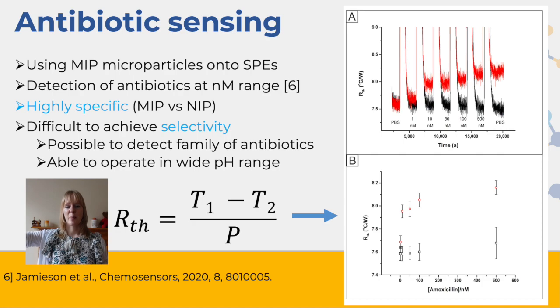And we see there's a gradual step for your molecularly imprinted polymer when you start to increase the concentration. And a spike means that every time we did a new addition, as soon as you introduce some liquid to the system, you will see a temporary drop in the temperature due to the addition of a cold liquid. But then, as soon as it stabilizes again, for the NIP you almost see a spike, and then it's back to the baseline. But if there's binding to your polymer material, your baseline will end up higher. And that's because binding increases the thermal resistance at the solid-liquid interface. And you can use that to convert it into what we call a dose response curve, where you look at your response, in this case the thermal resistance, and we look at a percentage increase over the concentration.